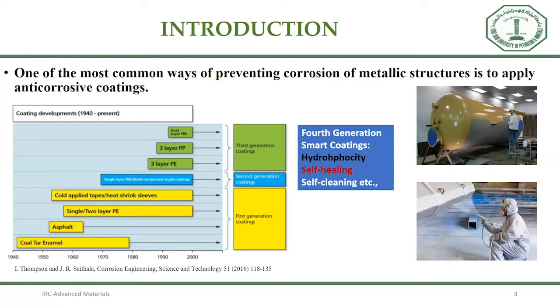Then after developing the fusion bonded epoxy coatings, we started to use a single layer FBE along with multi-component liquid coatings to control corrosion on metallic materials. That can be referred to as a second generation coating. Then we started to use polyethylene or polypropylene 3 layer multi-coating techniques along with some dual layer fusion bonded epoxy coatings. That can be referred to as a third generation coating. So now the research and development activities are moving towards the development of smart coatings that can have different multifunctionalities like hydrophobicity, self-healing, self-cleaning, and so on.